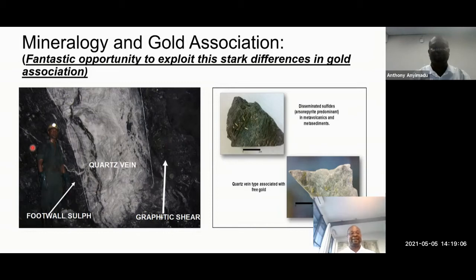So this example I'm showing is one of our AGA plants, and you look at it and it's like day and night underground. The material in situ is quartz, which is quite grayish, milky, and the rest are greenish black. Fortunately, or even more importantly for us, the mineralogy and the gold associations are made of mainly these two. One is sulfides, arsenopyrites mainly, and the other is quartz. The quartz is, of course, free milling gold. With the right grind, you get recoveries in the 90s, like a South African ore.